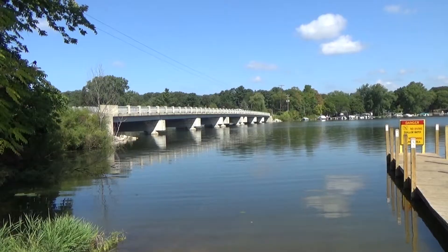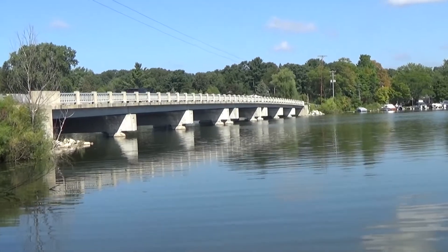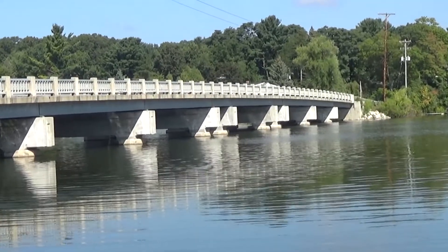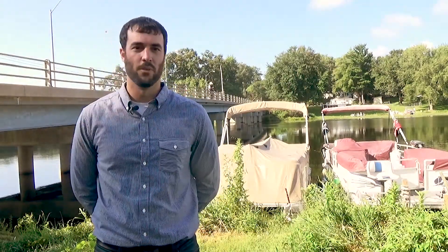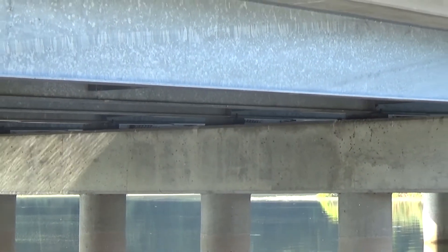We also used the same galvanizing on steel beams for Fruitport Road Bridge over Petty's Bayou. That was reconstructed in 2007 — we removed the existing beams and had them shipped out to get galvanizing put on, specifically because of what we have with this bridge here and how well the galvanizing has performed since 1966.